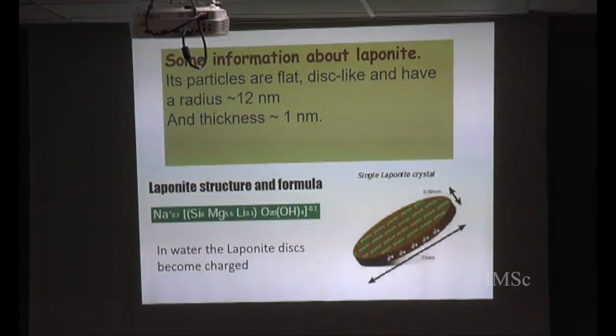So we use laponite, which is a very well characterized material. The laponite particles, like any clay particle, are flat layered structures, and they are nano-sized. The diameter is around 25 nanometers for the laponite platelet, and the thickness is very small, of the order of 1 nanometer. This is the chemical formula.